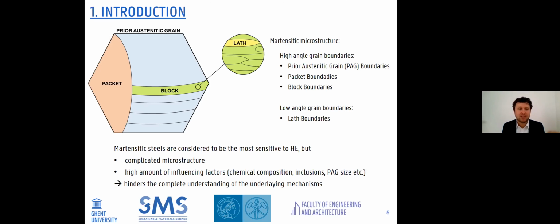Next to the quite complex microstructure, we also have additional influencing factors. For instance, the chemical composition, possible inclusions like alumina or MnS, and the grain size, the prior austenitic grain size. This hinders the complete understanding of the underlying mechanisms. Therefore, we focused on a quite fundamental approach to systematically target these materials and evaluate their trapping and embrittlement behavior.